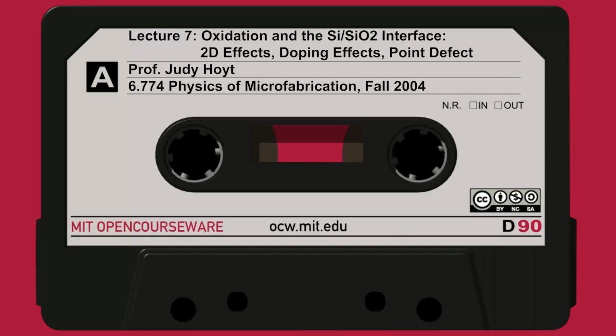So that we really can't get away from, and that's because the oxidant diffuses underneath that nitride, causes some oxidation, and the exact shape of the bird's head depends on, of course, what kind of stress model you use. But it's better than it was before. The lithography has a flat surface here, a flat here, but it's got this little bump here, which is not so easy to get rid of.